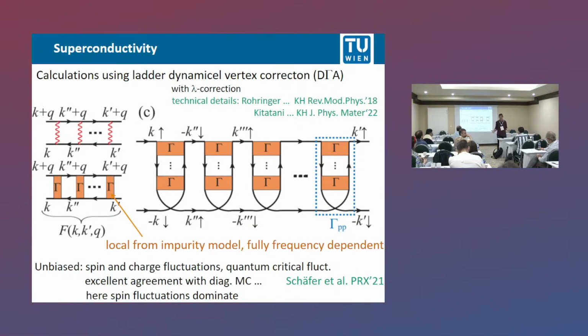But for experiment, it's also much closer to experiment. We have learned yesterday how large systems you need to really see a Kosterlitz-Thouless transition, and also since you have the coupling between the layers, your correlation length becomes exponentially large, and then you easily order, even if the interlayer coupling is very weak.